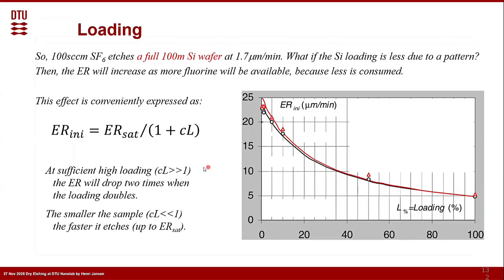But if you go further and further and you make your sample smaller and smaller, there's a moment where our initial thought that the etching will be totally independent at the surface, so that everything happens very quickly, is just not true anymore. So you get diffusion problems, you get temperature problems at the surface, and it just cannot go faster. So the supply, so the final reaction, is not fast enough. This number here can be controlled by temperature, and this one is more or less controlled by amount. And this is how this curve works.